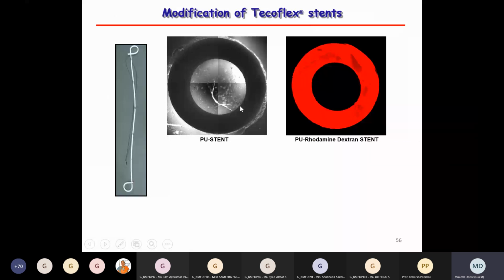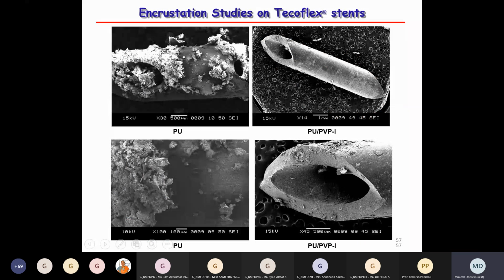So we took the entire stent and did the modification, and then we tried to monitor how the bacterial attachment takes place. You can see on the left-hand side, the unmodified surface has a lot of salt. On the right-hand side, the surface looks very good. The modified polyurethane surface looks very good.